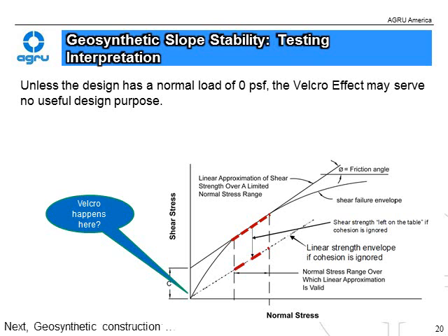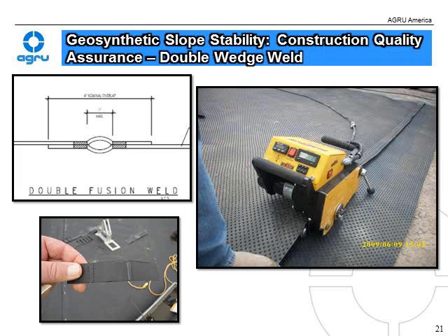Now, towards construction of geosynthetics. First thing I'm going to show you here is with geomembranes, in particular polyethylene geomembranes, is the double wedge weld. Now, this is a thermal weld where this machine here produces a weld that looks something like this in profile. The lower sheet and upper sheet are fused together here and here, leaving an air pocket here in between them. And then a cut strip from that weld looks something like this. You can see the fusion weld on this side, and then over here on this side, with the air channel in between them.